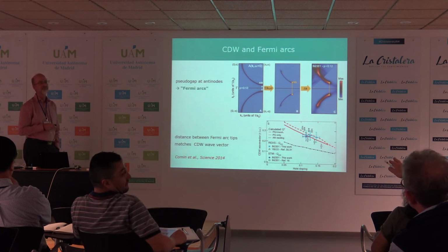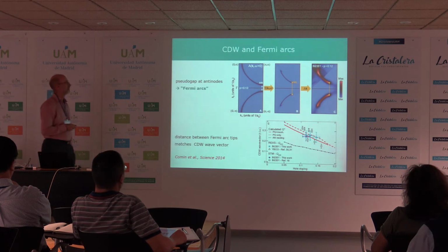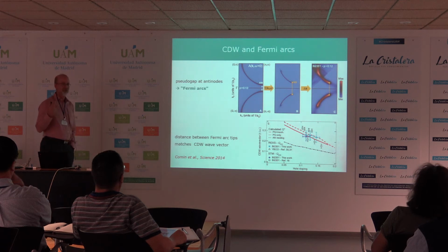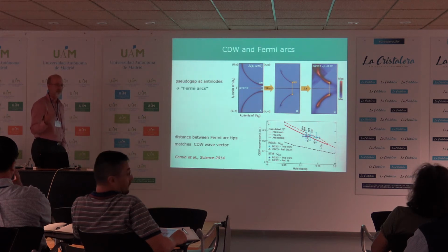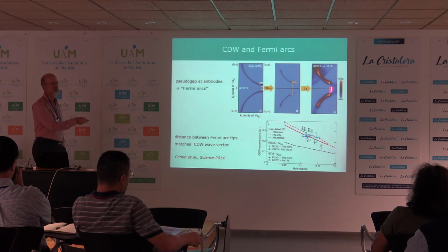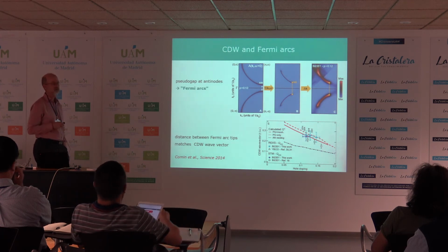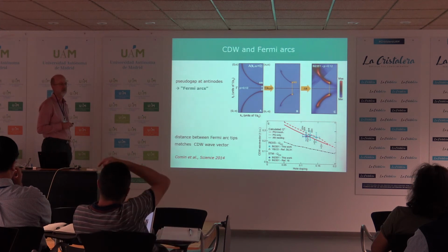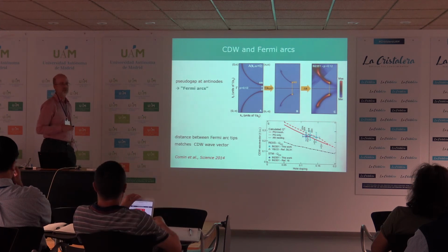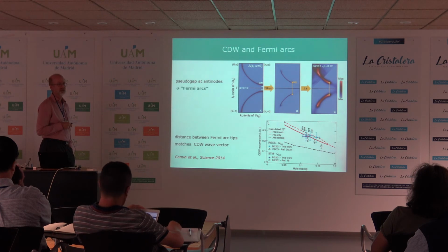But that's not consistent with the charge density wave, because there's no gap. If you had a truly long-range ordered charge density wave, you would, of course, see a gap here, right? And that's not the case, right? So things are certainly more complex. So it's not like a standard charge density wave.